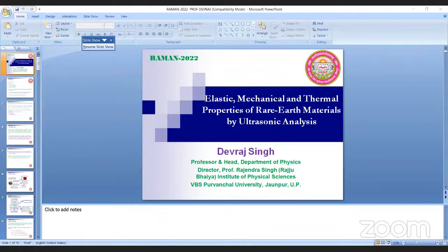The order of the thermal relaxation time for these materials is found to be the picosecond order. The order is different for the different types of material. Either it is 10 to the power minus 11 or 10 to the power minus 12 second. If it is 10 to the power minus 12 second, this confirms the semi-metallic behavior. If it is 10 to the power minus 13 second, then we say the material is a semiconductor. So this is important for the classification of the material.